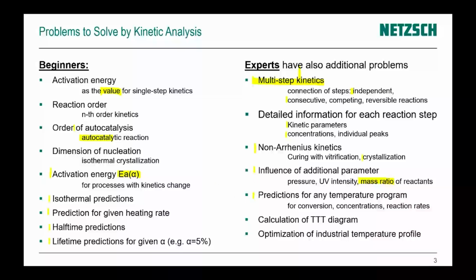We can make predictions not only for isothermal conditions, but for any temperature program. We must find conversion, concentration, reaction rates. We can calculate a time-temperature-transformation diagram in order to see where we have the vitrification line, where we have the gelation line, where the gelation point is at any temperature conditions. And it could also be optimization of an industrial temperature profile. So here we have very simple questions for beginners, very, very simple, and some more complex.